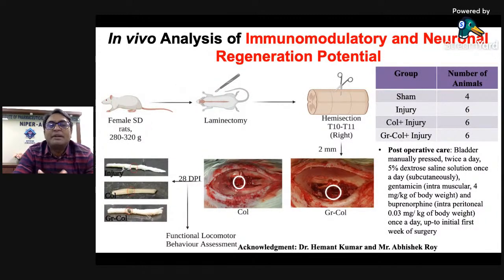We further tested our material in vivo in a rat model. These are the groups of animals we used: sham (healthy), injury, collagen alone as control, and our tested material, collagen Gr-Col. We performed a hemisection model at the T10-T11 thoracic region, creating a 2 mm gap where we implanted the material, collagen alone and Gr-Col.